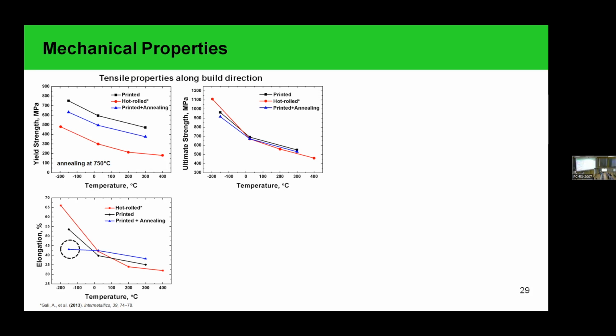And we applied annealing at 750 degrees Celsius, which we chose according to a previous publication for this material. According to the results, we see that the strength property for this material is typical as for conventionally produced materials. Here we compared our printed and annealed materials with the four-component system which was arc melted and further hot rolled, and the strength characteristics are approximately the same.